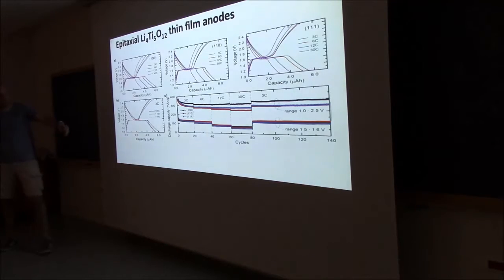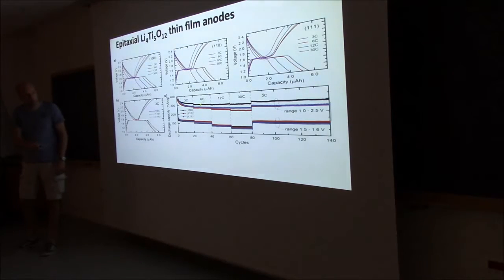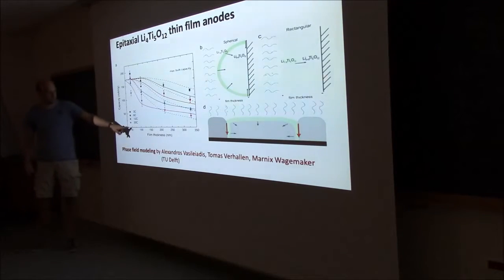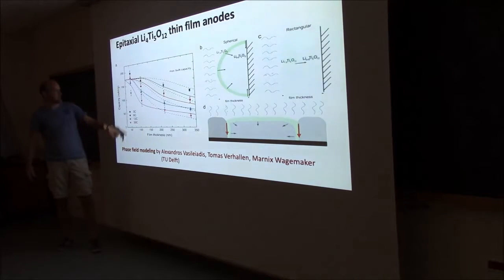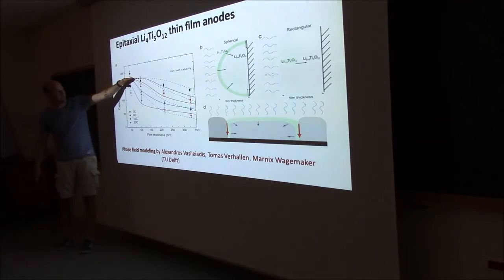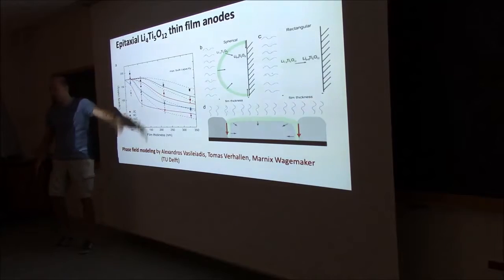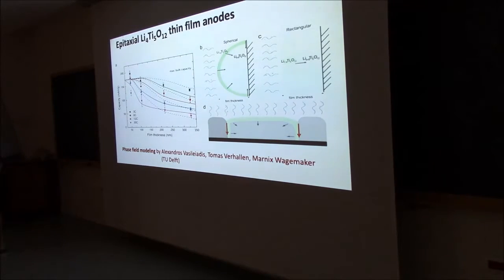Now, when we took those numbers, different speeds, different C rates, and we do that for the different thicknesses I've shown you before, you put them in a diagram where you have the different thicknesses, the capacities, and with colors the different C rates. You can see that when you make something thin and slow, you have a very high capacity. But if you make it thicker and faster, you cannot extract all the lithium out of it very easily. So we thought, okay, that's something we should be able to model to see if that fits.